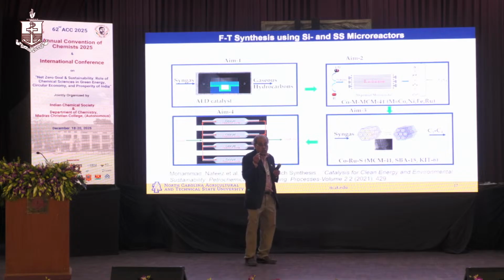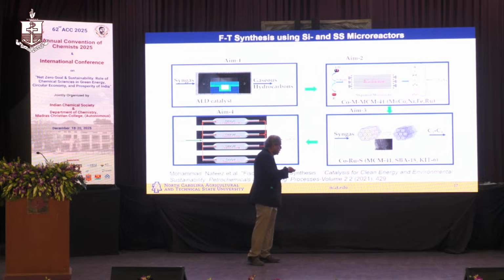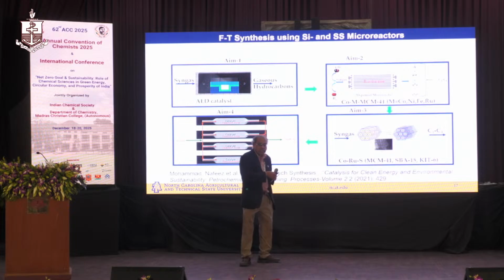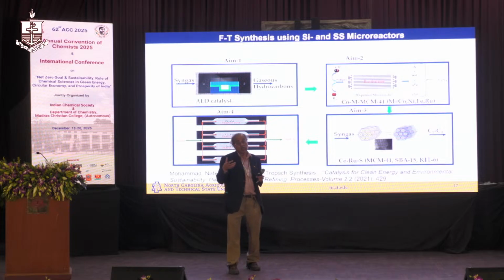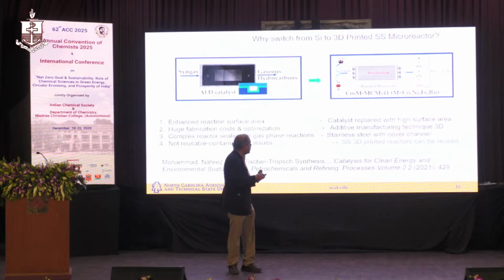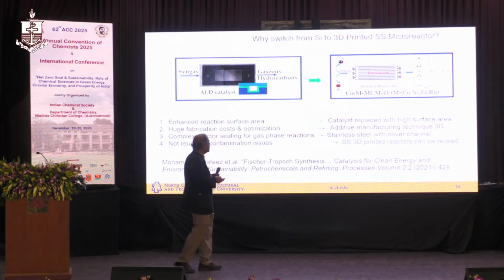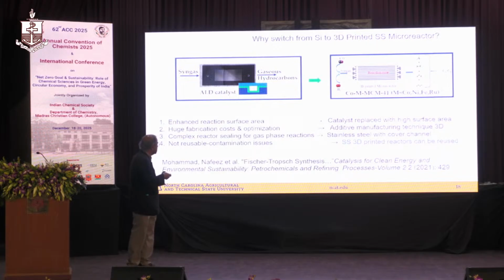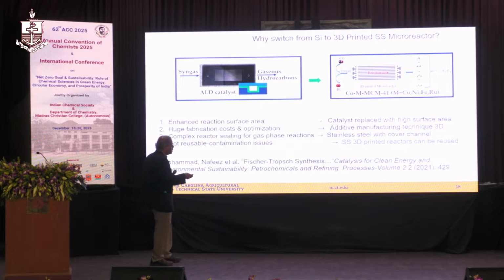you are going to lose the surface area quite a bit because the channels are 500 micron. And we use mesoporous materials like MCM41 and SBA15, where you can get a lot of surface area instead of the sol gel that I told you. Okay? Now you see, this is the main reason. So you see, you can enhance the reaction surface area, huge fabrication cost, all this, and then you can use